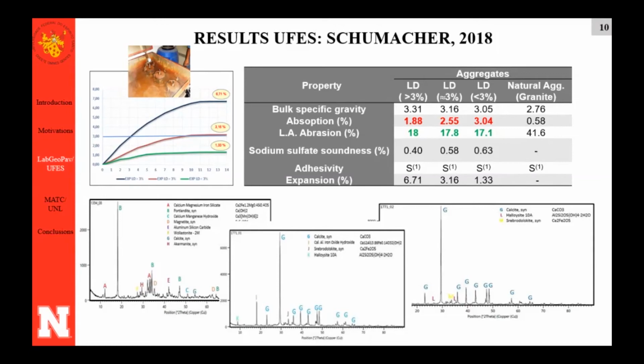We also evaluate the chemical changes. When the level of expansion decreases, we can see that at the beginning, when the slag comes as is, you have a wide range of chemical components. And as we cure the material, it looks like we have a stabilization of the chemical components present in the slag.